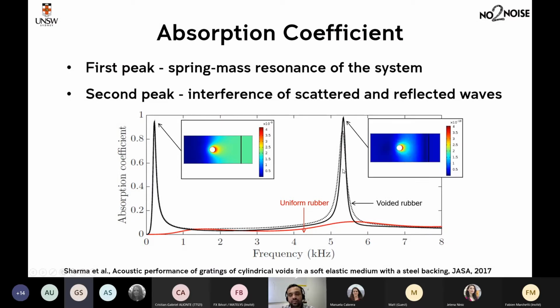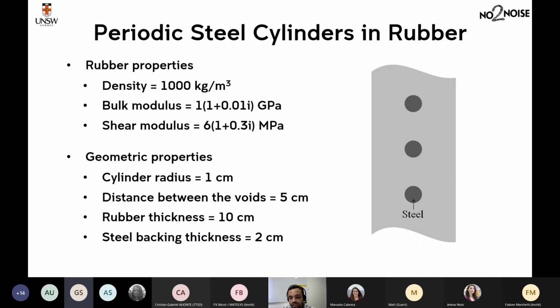The second peak is this: you have your incident wave in this direction. It gets scattered from the cavities in different directions. Some of the incident wave reaches the steel backing and gets reflected. The second peak is created when there is interference between the waves reflected by the backing and those scattered by the cavities. That interference also leads to a peak of very high sound absorption. And this is periodic. If you go higher in frequency, you will see that this is periodic in frequency. This was for voided inclusions.